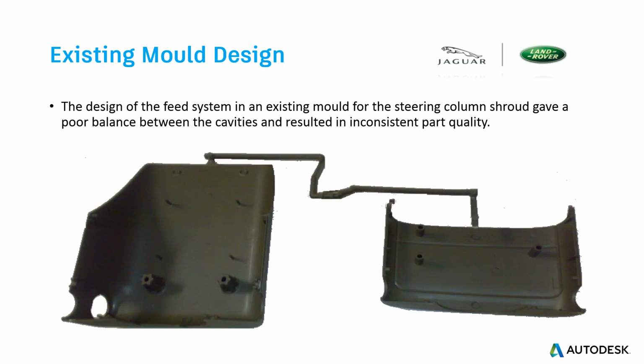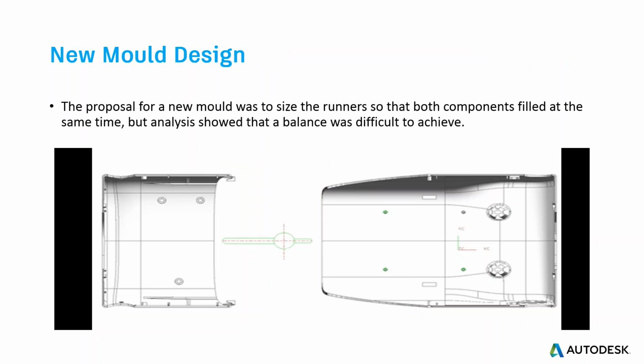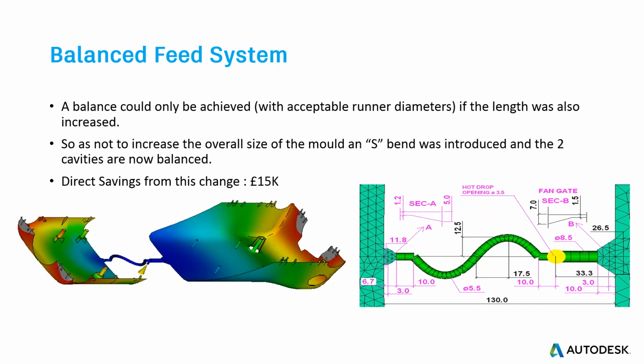So one of our customers, Jaguar Land Rover, they had a 1+1 tool, and this gave problems during injection moulding. It's a poor balance between the cavities, and it resulted in inconsistent part quality. They couldn't get the sizes quite right for both of them. So they looked at resizing the runners, but it was difficult to achieve with the existing runner design. So the only balance that could be achieved was with an S-shaped runner, so it actually gave a longer length to balance on, and that was very successful, and that gave them some savings just on that one tool.